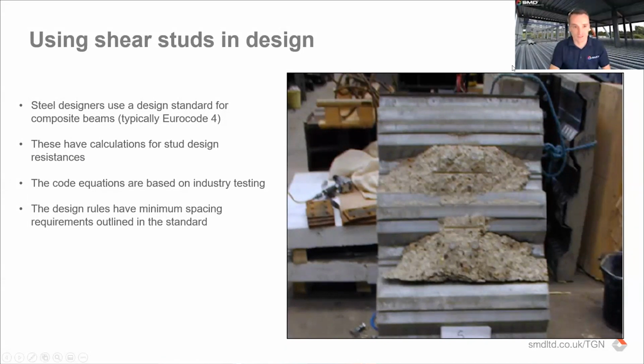So using the shear studs in design, and that's leading on from the KT factors. The designers of the composite beam, and I know some of you out there will be designers, will use a design standard. In the UK, typically that'll be Eurocode 4, or it may be BS 5950. They have calculations for stud design resistances, which we've just seen the ones for Eurocode 4. And those code equations are based on certain industry testing. Some of that's collaborative industry testing, some of it will be individuals testing. So this picture on the right here is a test that we had on a previous product of ours. You can just about see the 2 shear studs here, and then this cone of failure that I showed in the other section earlier.